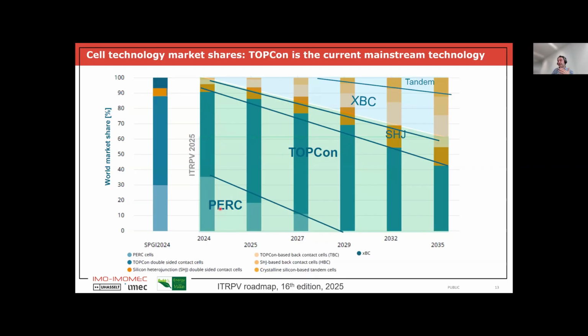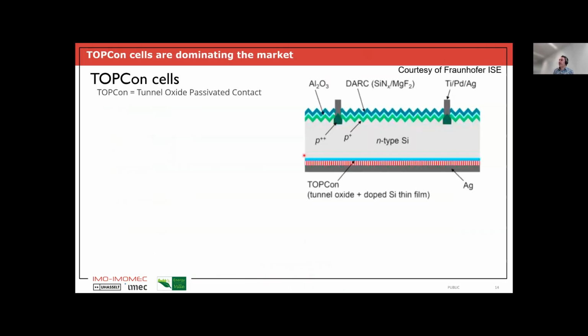Why did we switch in the industry from PERC to TOPCon now? That is simply because with TOPCon, you can go to higher efficiencies. With PERC in industry, or let's say in the lab, you can reach 24%. With TOPCon, as I will show you, you can reach close to 27%. So much higher efficiency. So it will lead to lower cost at system level. So the TOPCon cells, as I mentioned in the previous slide, are now dominating the market. And you see here the cell structure of such a device.